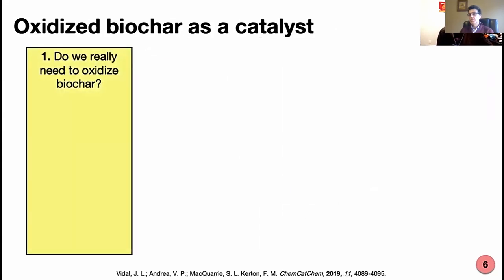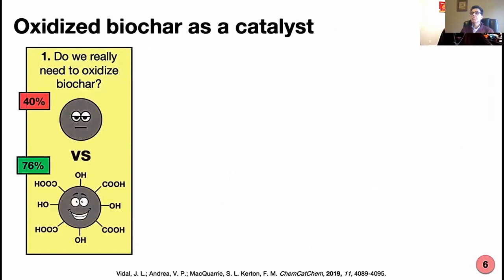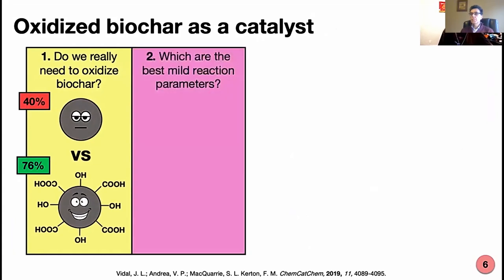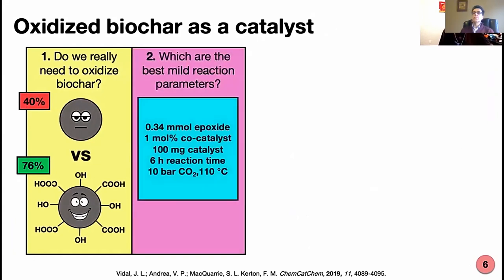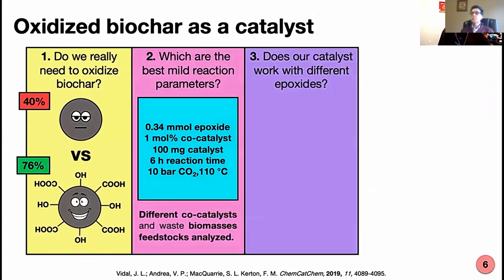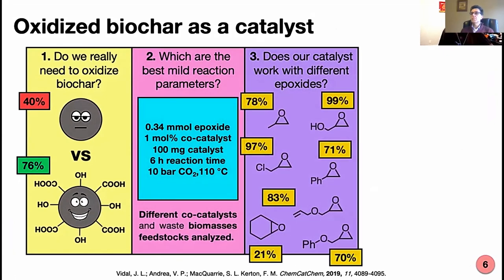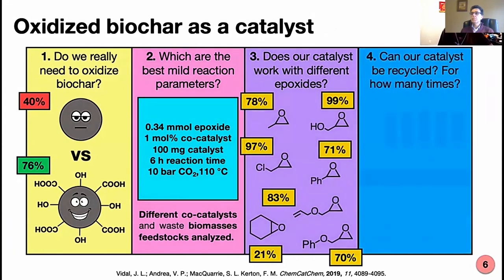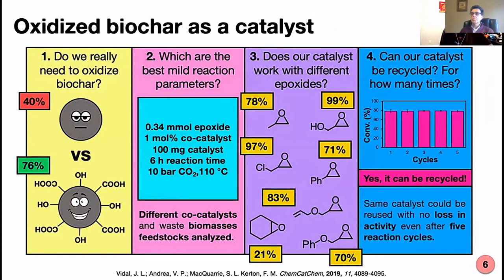During our studies, we found out that oxidized biochar could facilitate the reaction via hydrogen bonding, that biochar from different biomass feedstocks could be used to promote the reaction under mild reaction conditions, that a wide range of substrates could work for this catalytic system, and also that oxidized biochar could be reused for at least 5 times, being a sustainable, renewable, efficient, and also recyclable catalyst for the cycloaddition reaction between CO2 and epoxides.